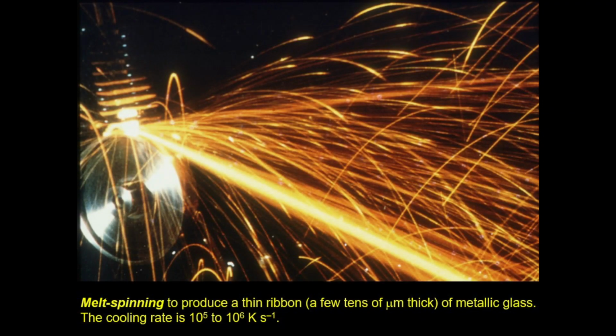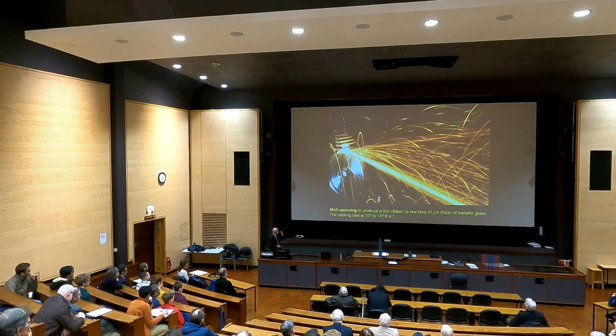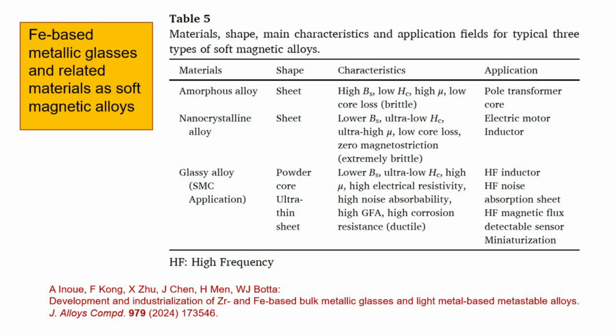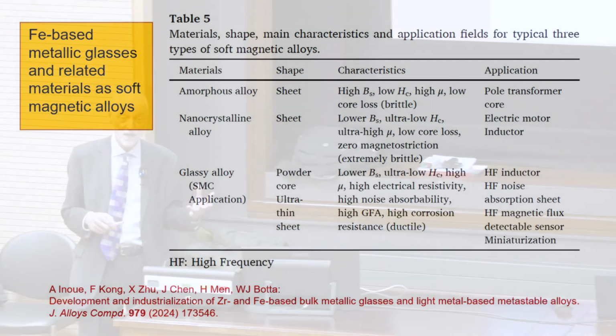I mentioned that you might have to cool rather fast. This is an example of a rapidly spinning wheel, hot liquid coming onto it. This ribbon comes off. It's a few tens of microns thick. And the cooling rate is anything from about 1,000,000 degrees per second down to 1/10 of that. So pretty fast cooling. And we should think, well, does this do anything for us? Well, this particular material, which comes off iron-based, remains the most important commercial application of glassy alloys.